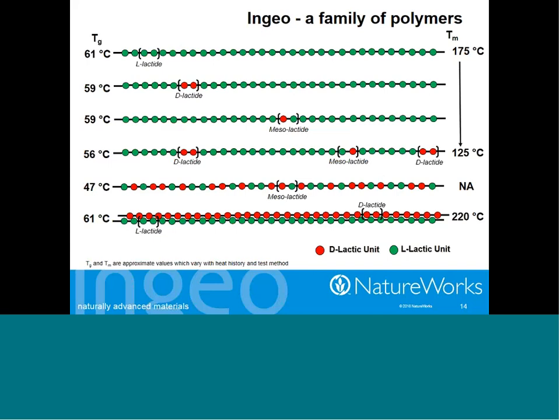The next slide gives you an indication of the various polymers that we make at NatureWorks, all the way from the top material, which is for all intents and purposes a true homopolymer of L-lactide. That would generally have a melting point in excess of 175 degrees. It would be a very rapidly crystallizing PLA material and crystallize to a great extent.